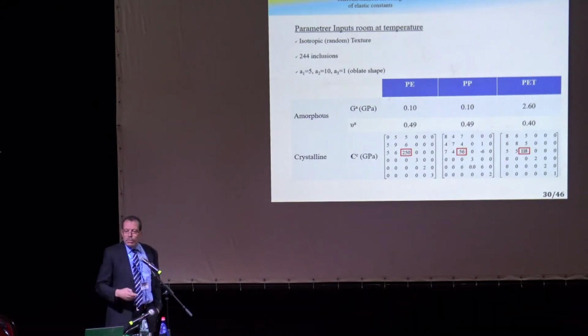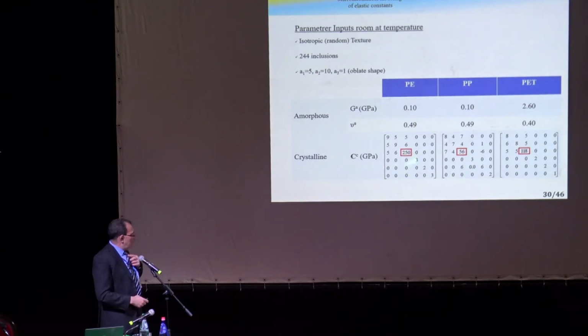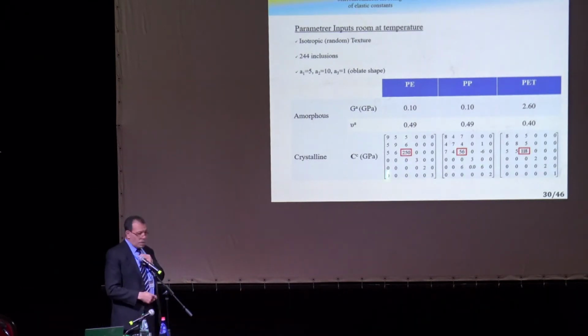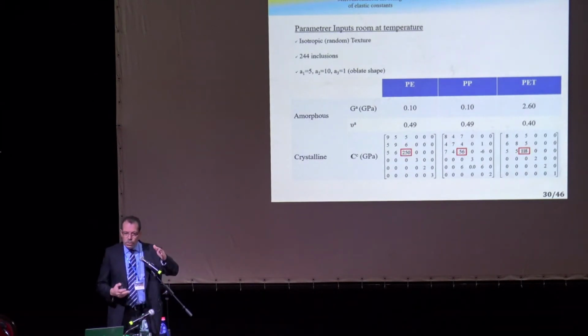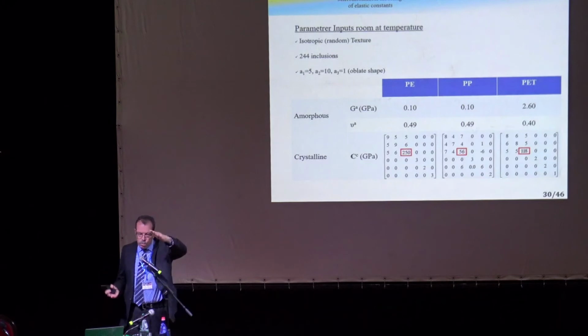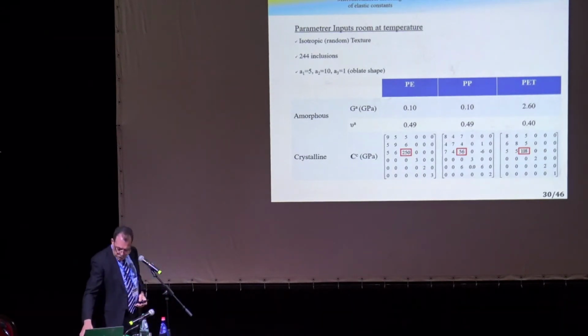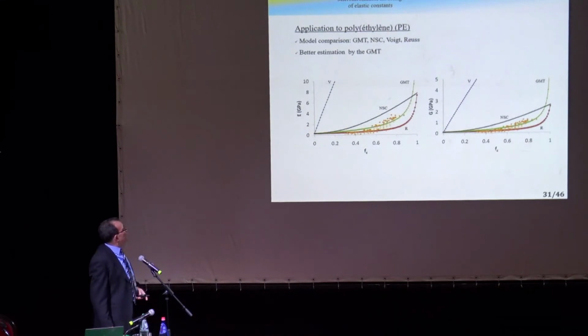If it's random, then you will get an isotropic answer, but still with this local anisotropy, or big contrast as we call it, you cannot rely on upper bound and lower bound. Why? Because there will be a huge difference between the two. When contrast is high, you have to look for intermediate modeling, and we are now looking at Mori-Tanaka and self-consistency to see what they will give us. This is the comparison: you see a huge difference between upper bound and lower bound. And this is the Mori-Tanaka, and this is the self-consistent based on this double inclusion modeling.